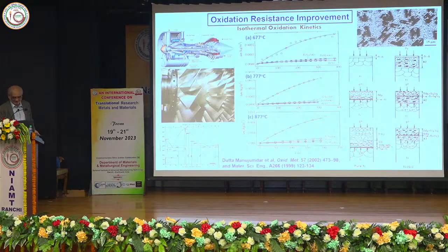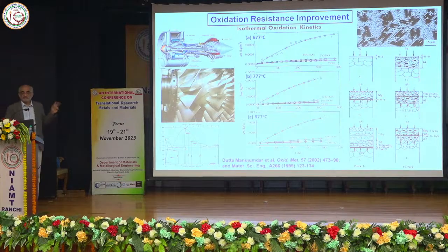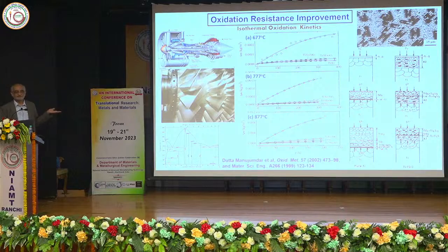I'll skip those details, but now the novelty that we wanted to propose. This was done more than 20 years ago, and this was one of the two PhDs of Jyotsna, who first showed that people always think of oxides as thermal protection. I think this was one of the first examples where she showed that if you have intermetallic phases - look at this phase diagram, this Ti5Si3, 2130 degree incongruent melting maximum.